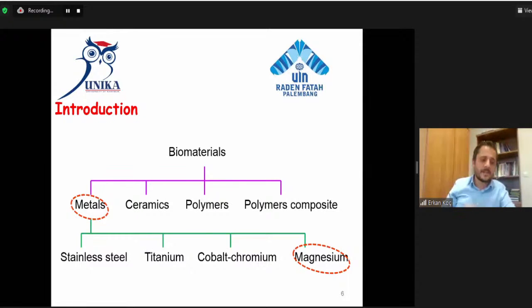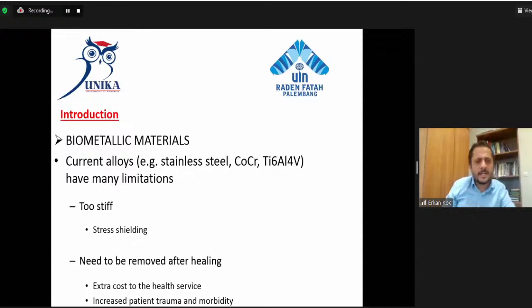However, these biometallic materials have many limitations. For instance, they are too stiff. It means the elastic modulus of these materials is much higher than that of natural bone. The serious mismatch in the elastic modulus will result in serious stress shielding effects, leading to reduced new bone growth. And moreover, they need to be removed after healing. It's extra cost to the health service. It increases patient trauma and morbidity. That's why we need some degradable biomaterials.